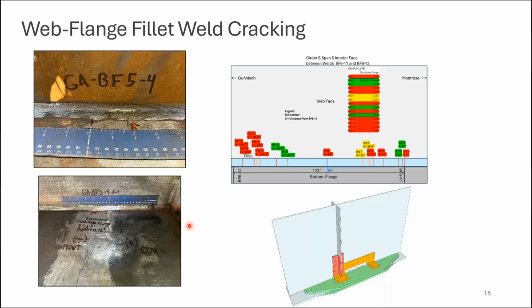With that 50 KSI material, it's so thick to get it to basically have the same capacity as the 100 KSI steel that we were running into some problems. But as we started seeing these fillet weld cracks as well, we switched directions. That really moved the goalpost, and we had to go in a different direction towards more global plating solutions.